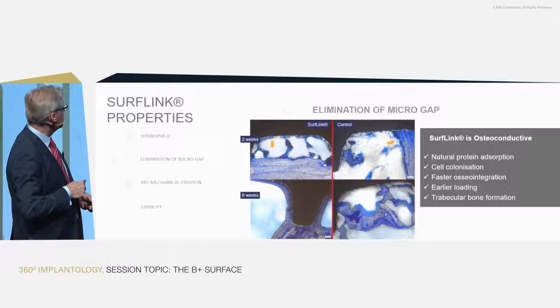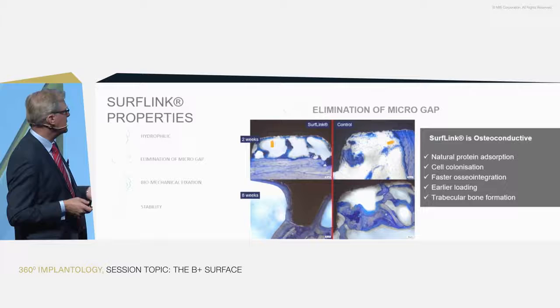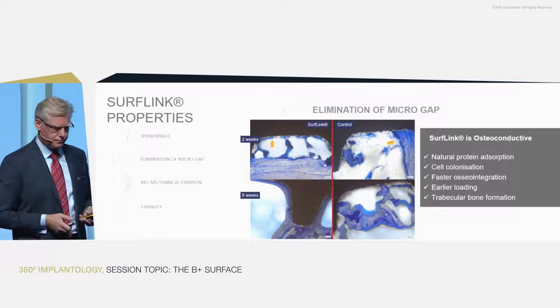After eight weeks, we see a thick layer lining up around the implant thread and connecting to the trabecula of the bone — a trabecular integration directly after eight weeks. On the control, nothing happened on the implant surface at either two weeks or eight weeks.